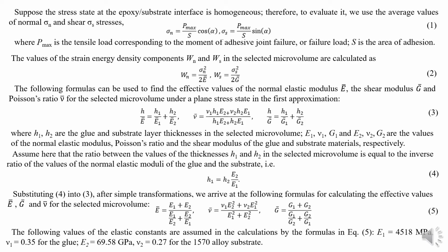The formulation of the local failure criterion uses the assumption that the strain energy density in a selected microvolume including the joint is the driving force for the delamination of the adhesive joint under a force action. For this purpose, a microvolume simultaneously belonging to the glue and the substrate is conventionally selected on the joint, inside and along which slippage and delamination are prohibited. The values of the strain energy density components Wn and Ws in the selected microvolume are calculated by formula 2, where E and G are the normal elastic and shear modulus respectively.